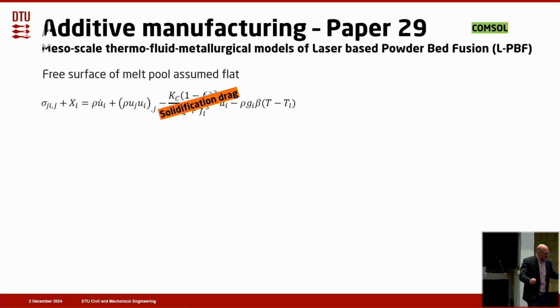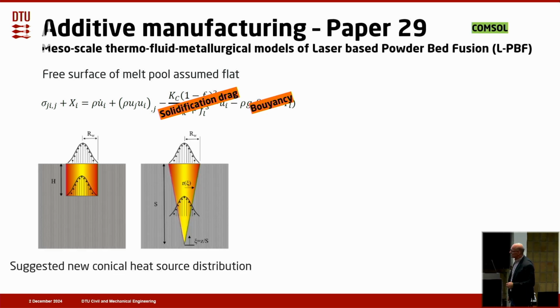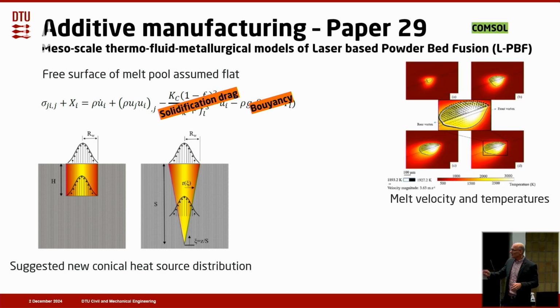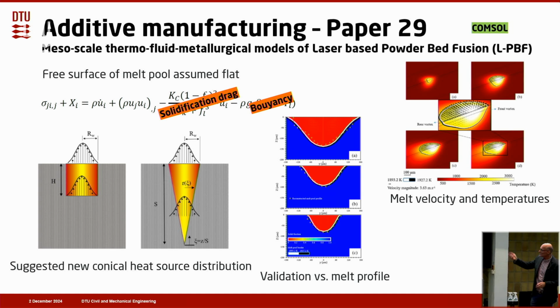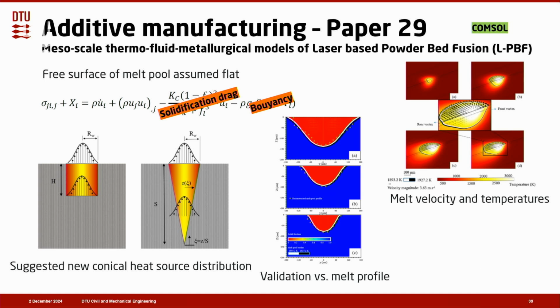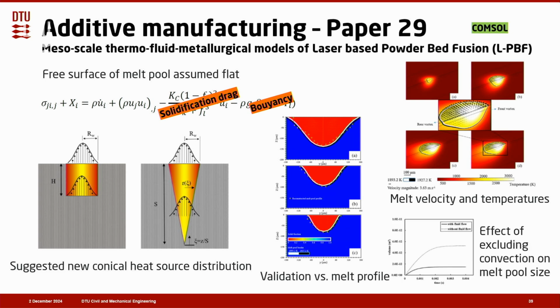So what we continued with was a mesoscale thermofluid metallurgical model of laser powder bed fusion. Here we have the momentum equation. We assumed that the melt pool surface was flat, so we also here included the solidification drag and the buoyancy. And then we suggested a new conical heat source distribution and could calculate melt velocities and temperatures. We validated against a melt profile from literature, and we got very good agreement. And then we also analyzed the effect of excluding the convection on the melt pool size. Of course, if you exclude convection, you don't have as much cooling as if you include it, and therefore the melt pool size increases when you only have conduction.